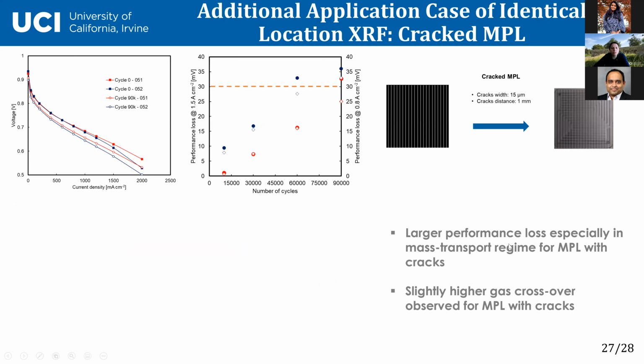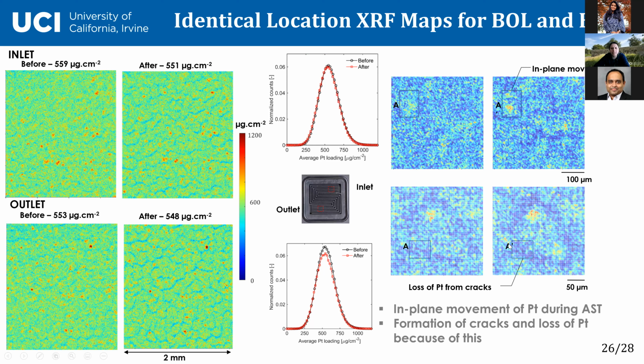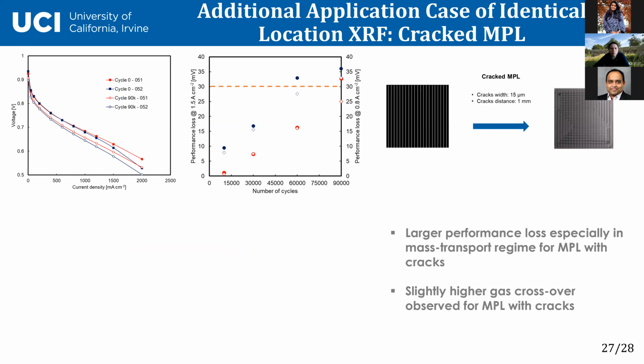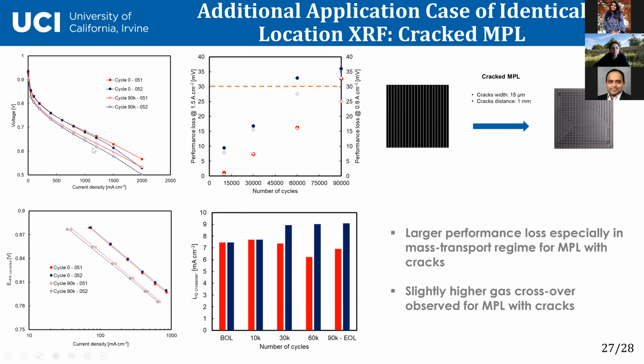But we also found another application of this method. So since we were studying effect of cracks in microporous layer, we made microporous layer with really well-defined cracks, 15 microns each crack, distance 1 millimeter. So we saw that performance didn't improve with cracks. So black one here is with cracks, red without cracks, beginning of life, end of life. So cracks really hurt the performance.